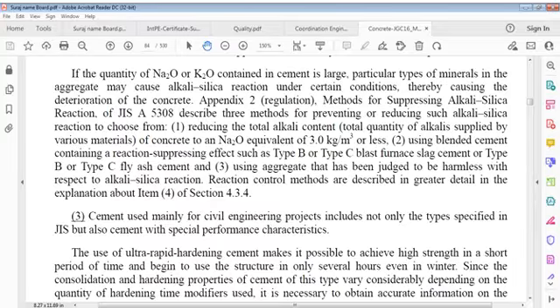So first is reducing total alkali content, that's total quantity of alkali supplied by various materials of concrete, to Na2O equivalent of 3 kg per cubic meter or less. Then second is using blended cement containing reaction suppressing effects such as type B or type C blast furnace slag cement or type B or type C fly ash cement, and third, using aggregate that has been judged to be harmless.